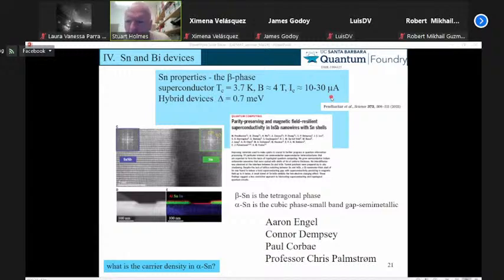And I'm just showing you a publication here from 2021. That's my collaborators in California. They grow this material. They published a paper on this in the region of quantum computing. They can grow tin on indium antimonide. This is in the beta phase, but it also grows in the alpha phase. If it's grown at low temperatures, the tin can go down in the so-called alpha phase. And it's a small band gap semi-metal in the alpha phase.